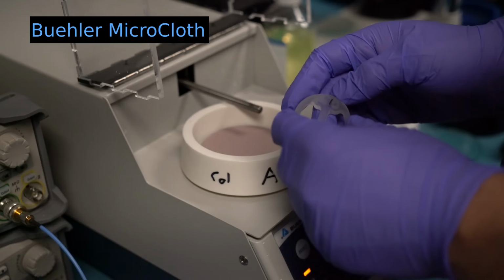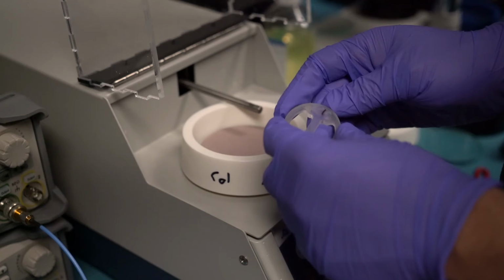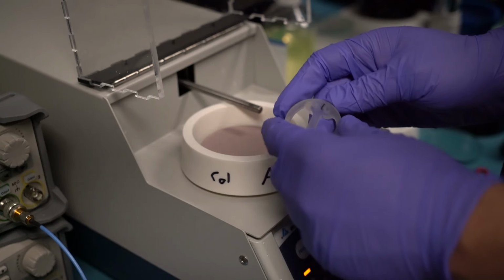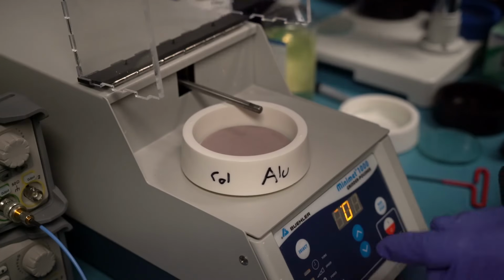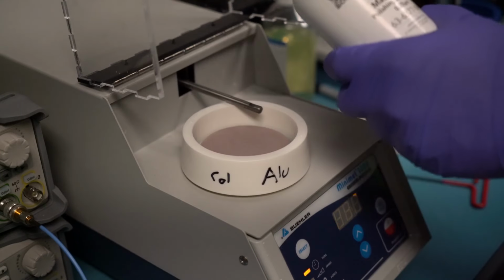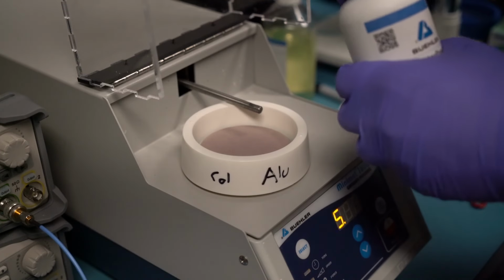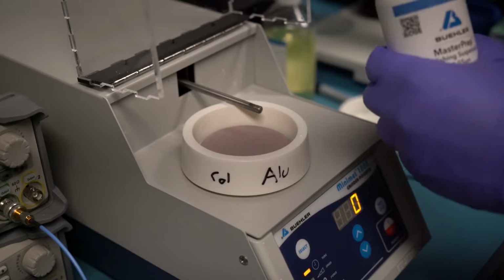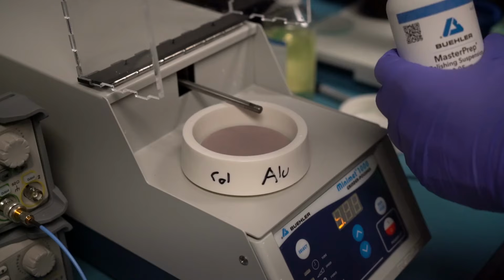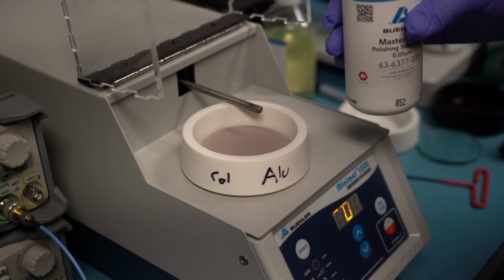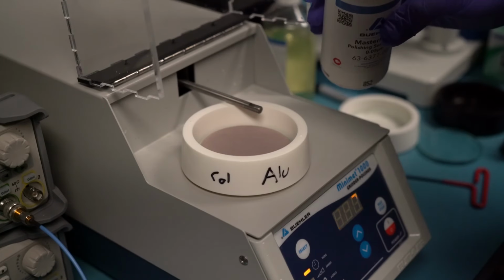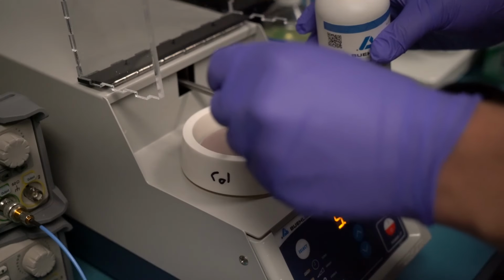So it's now been probably 10 or 15 minutes at the 1 micron diamond, and the surface is looking pretty good. We just need to give it that last final shine before we can go get some really pretty images out of it. And for that, I'm going to try some colloidal alumina, 50 nanometers. Silica might actually work well as well. In my experience, alumina gives good results on copper. There is a little bit of copper in the die attach paddle, and so for that reason, I'm going to try to use the alumina, and we're going to see how it all works.